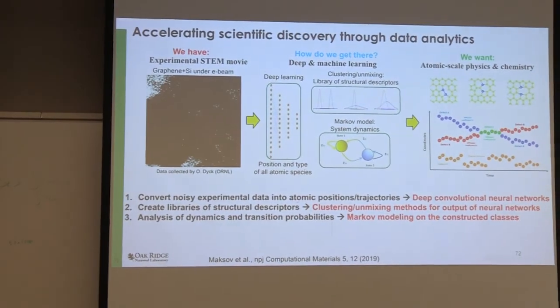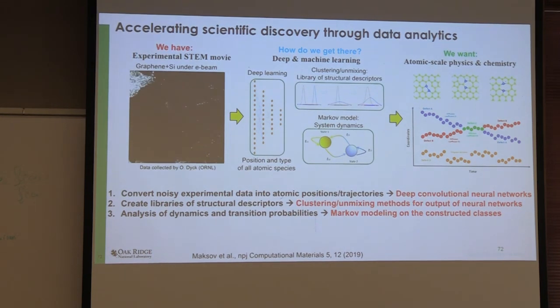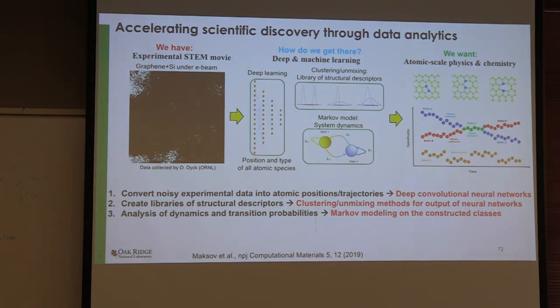But for imaging, the best technique is a convolutional network. It does exceptionally well. So typically, we will use a convolutional neural network to go from an image that's collected off of an electron microscope to the data that is analyzed by the machine learning directly. That convolutional neural network, which just looks something like that, a bunch of nodes and different convolution layers, is able to do that with quantitative precision, 99% accuracy. Not too bad. So it's pretty robust. And then you can extract out some of the physics using clustering methods. I won't go through that in detail, but I'm glad to talk about it during questions.